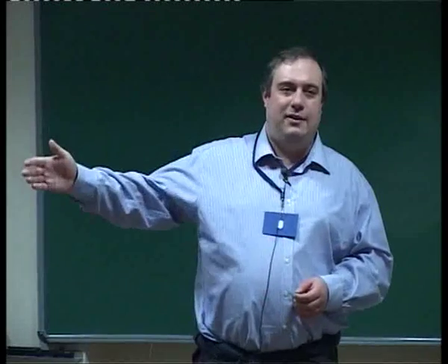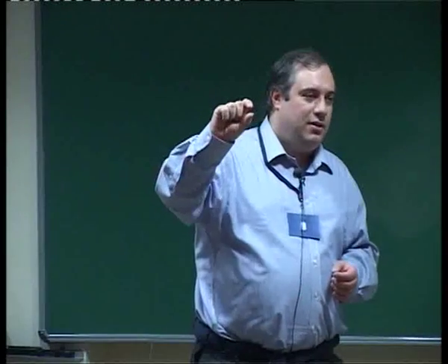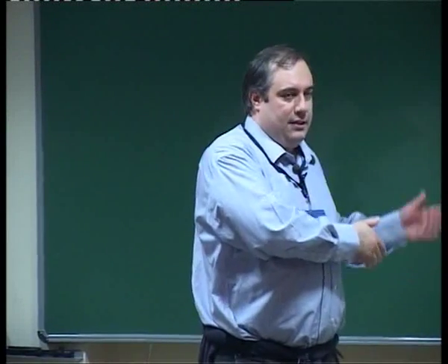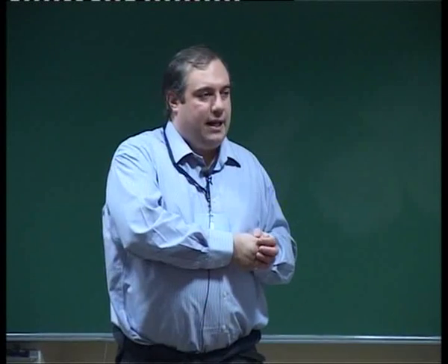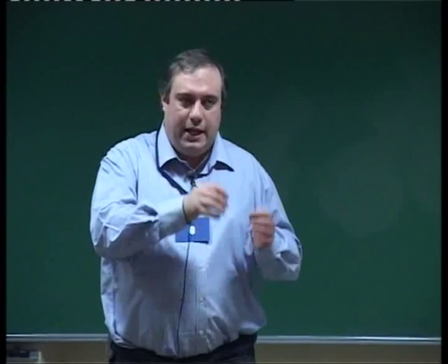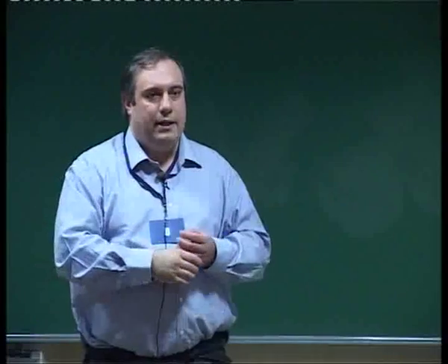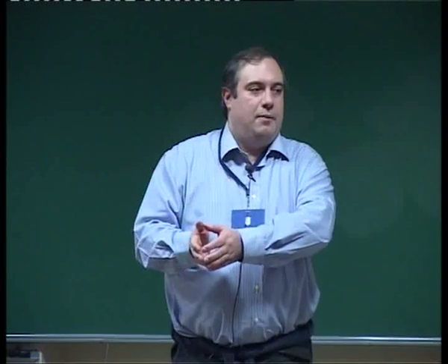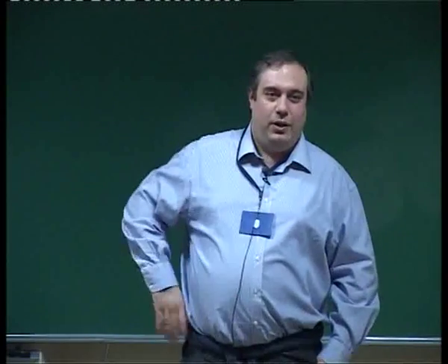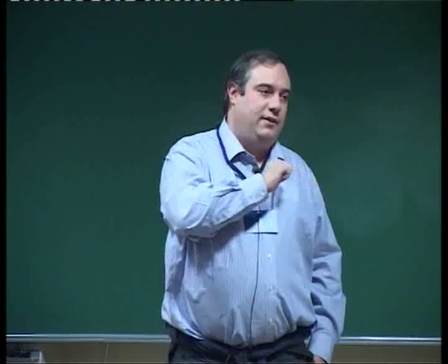Of course, there is a trick in everything, because in one side you lose the tunability. The semiconducting nanocrystals are very slow. So in principle, graphene is ultra fast, 10 femtoseconds. I don't have time to show the ultra fast dynamics, because very recently we have started with 7 femtosecond resolution lasers, the electron-electron interactions, the evolution of a population of hot electrons in graphene while it's spreading out. But you lose that if you use another material that is very slow. So everything you have to give something, but all these fronts are very new, so all of them are continuing.